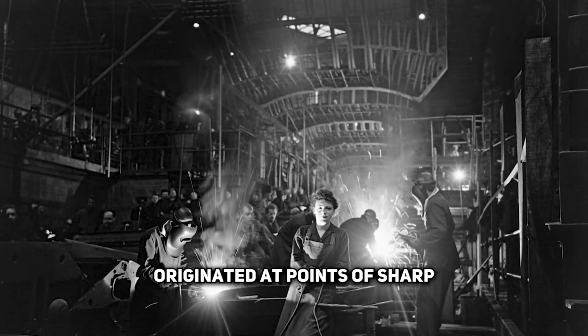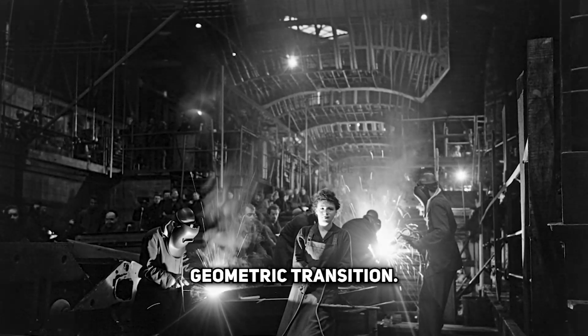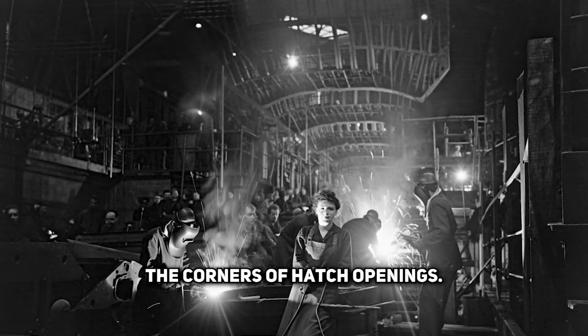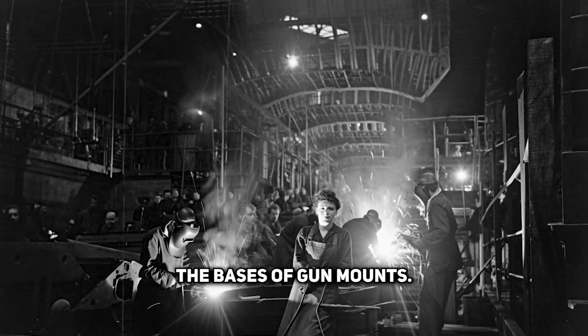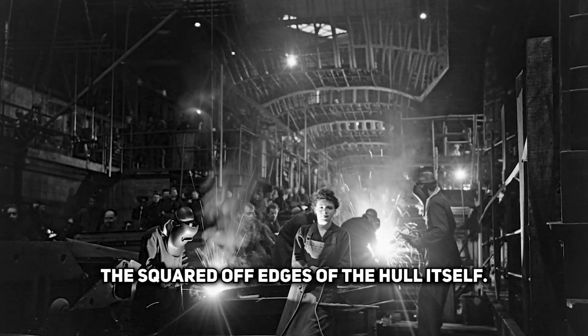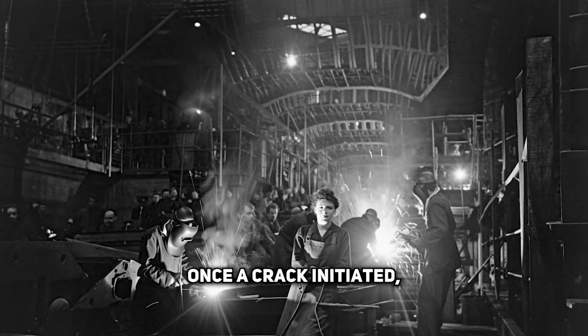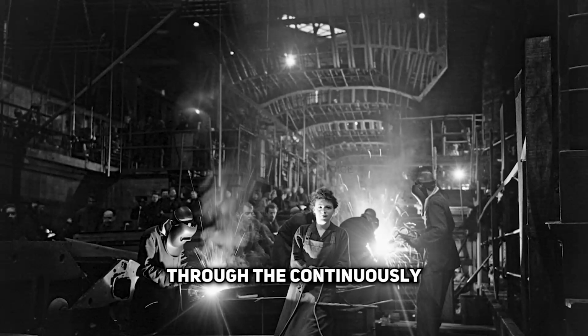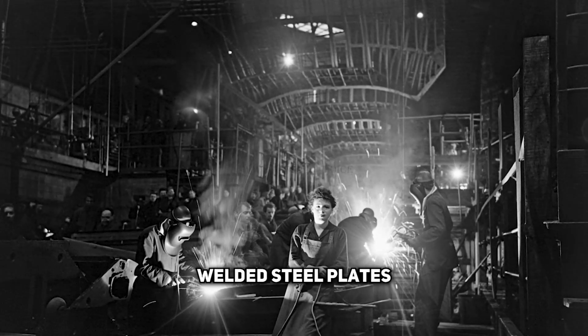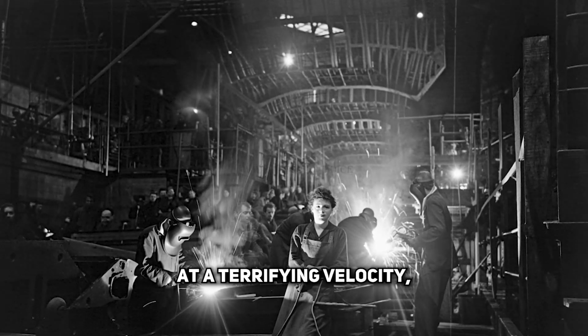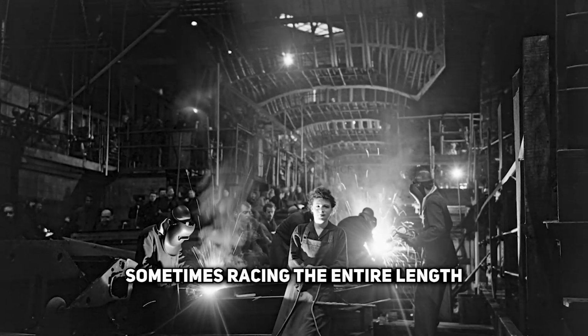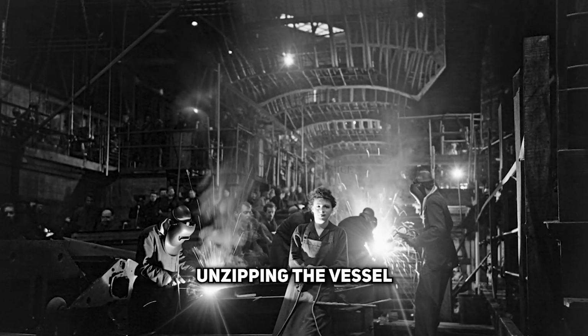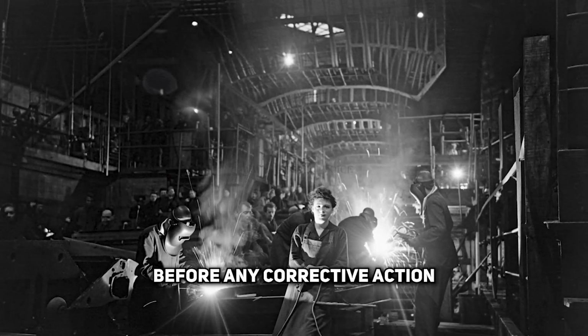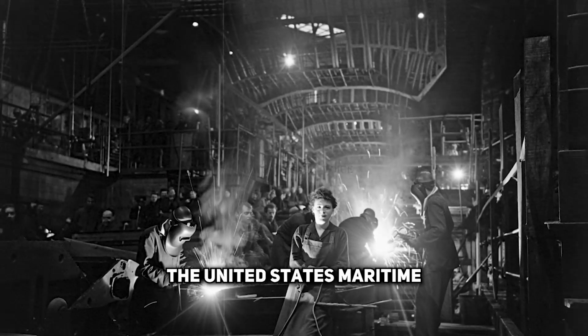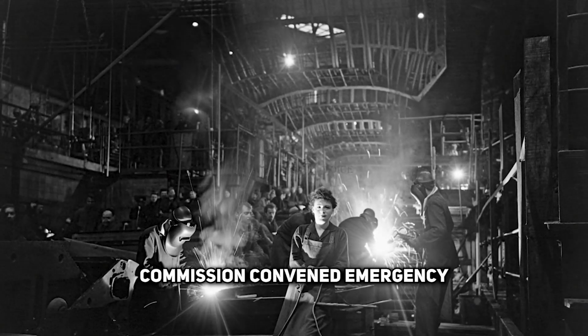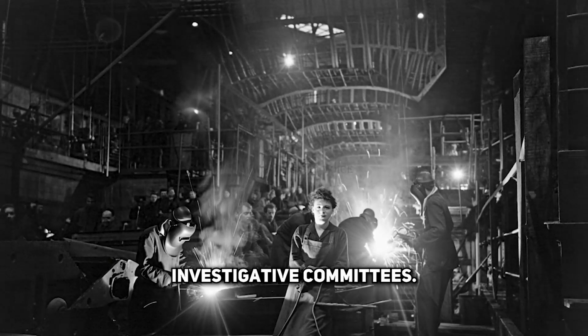The cracks typically originated at points of sharp geometric transition. The corners of hatch openings, the bases of gun mounts, the squared-off edges of the hull itself. Once a crack initiated, it would propagate through the continuously welded steel plates at a terrifying velocity, sometimes racing the entire length of a ship's hull in a matter of seconds, unzipping the vessel before any corrective action could be taken. The United States Maritime Commission convened emergency investigative committees.